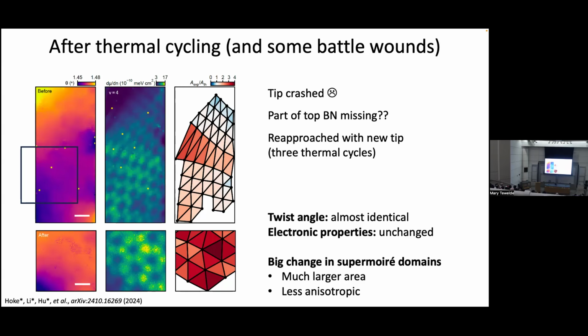That is, that's where you have the stacking faults, where the local stacking changes. But as long as the stacking within domains is energetically preferred, then growing these domains actually helps you energetically overall. And so my guess is the reason why we went to this more isotropic, larger configuration is really that the system prefers to have that as its lowest energy configuration.